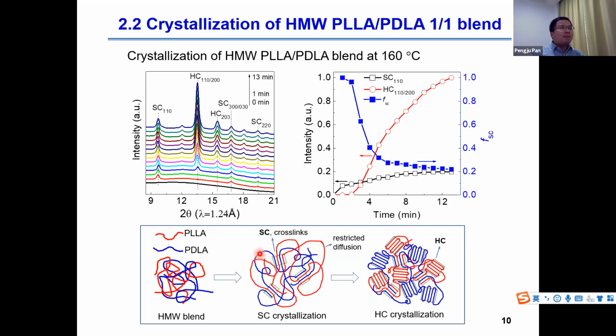We explain the crystallization of the high molecular weight blend. From this result, the stereocomplex crystal is first formed in the crystallization process. The formed stereocomplex crystal can work as a crystal link and retard the mobility of the linked polymer chain. On the other hand, it is reported that the stereocomplex crystal can work as the nucleating agent of homocrystal. Therefore, homocrystal is kinetically favored in the later stage of crystallization. However, because of the very low stereocomplex content, the effect of stereocomplex on the following crystallization process is not so significant. It just affects the crystallization kinetics, but not the crystalline structure of the homocrystal.